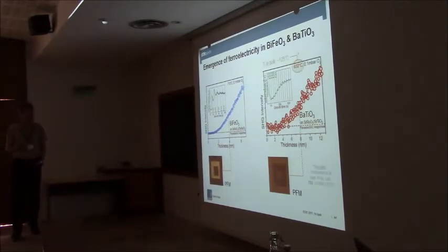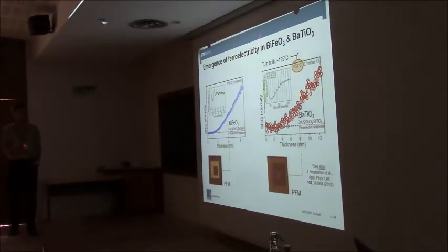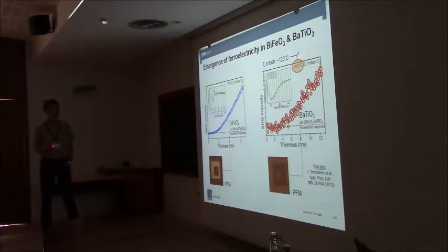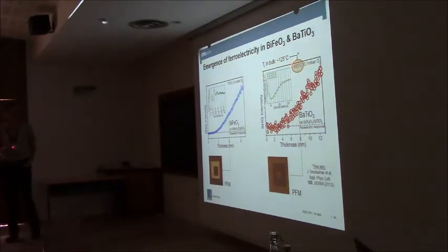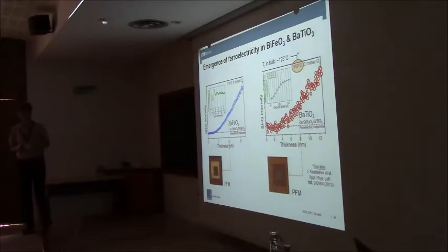Okay, that worked nicely. One other remarkable thing: in thin films, because of the strain and the induced dipoles, you can have grossly enhanced critical temperatures. Typically the Curie temperature of barium titanate is 125 Celsius. Here it's at least 650 Celsius. So that's another amazing effect that you have when you grow strained films.